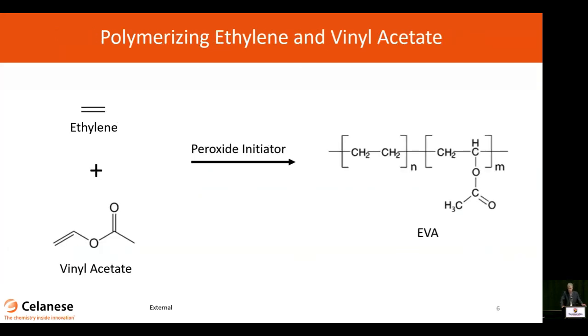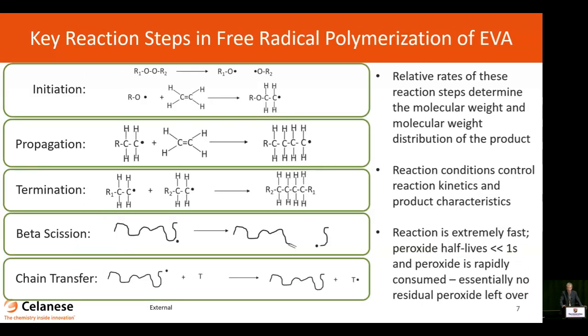So at a very simple level, the chemistry is pretty straightforward, right? You take ethylene gas, you take vinyl acetate monomer, you bring those two things together, you compress them to an almost alarmingly high pressure, introduce peroxide initiator, and you get a very rapid exothermic polymerization of a copolymer. But anyone who's studied free radical polymerization knows that there's a lot of different things going on. And so it's the relative rates of these various reactions that will define what the polymer structure is, what the polymer architecture is, what its molecular weight will be. So these are all very, very important. And at a practical level, you control these relative rates of these various reactions by controlling things like reactor temperatures, feed gas temperatures, reactor pressure, and a variety of other parameters that are locked in the product manufacturing specification.